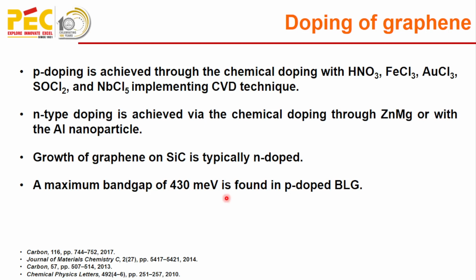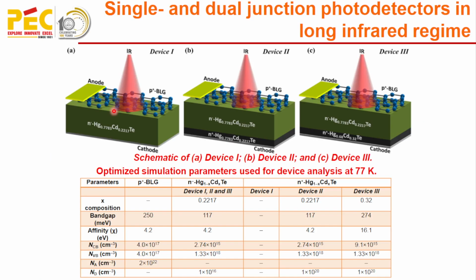Now moving to my work, which is the single and dual junction photodetector. For making the single junction photodetector, I took N-type, lightly doped mercury cadmium telluride as an active layer, on which we deposited a 2 nanometer thick p-type bilayer graphene, and the devices are top illuminated. So there is a formation of one heterojunction among these, and the X composition of the cadmium is tuned in such a way as to work at the long operating wavelength.